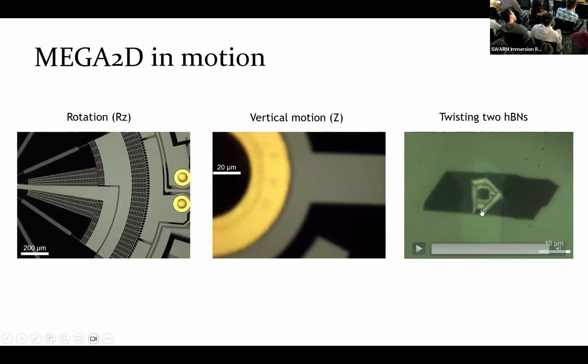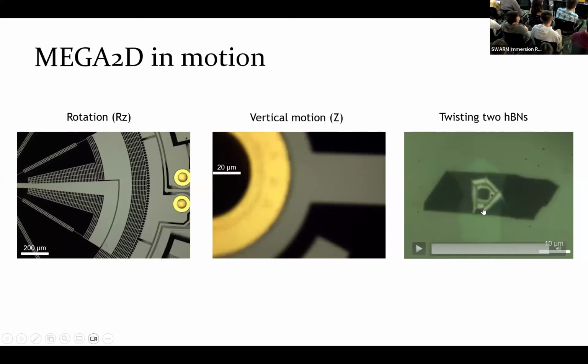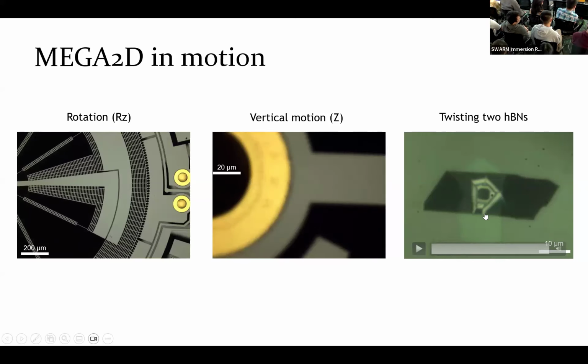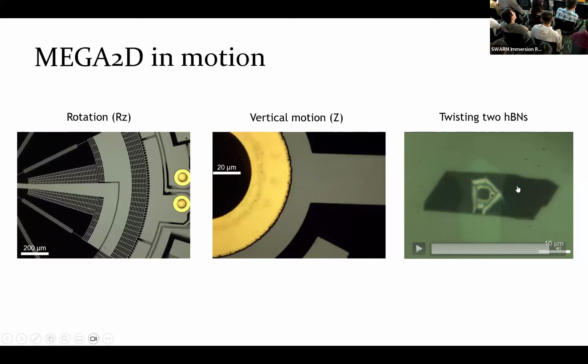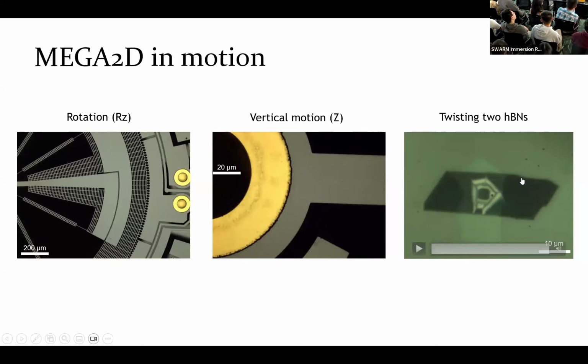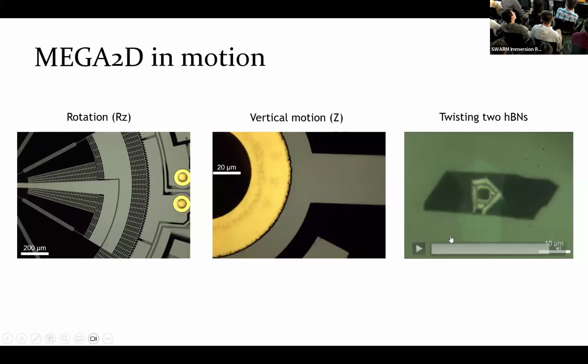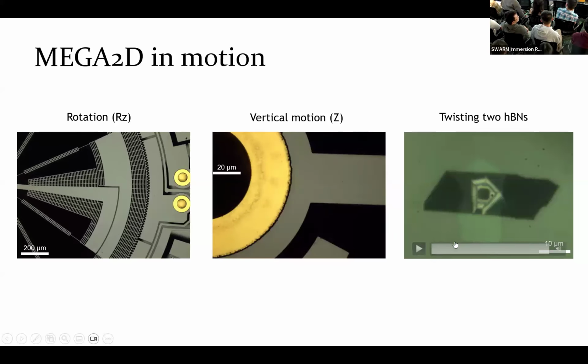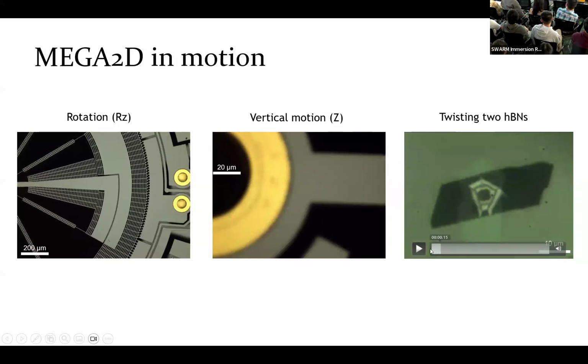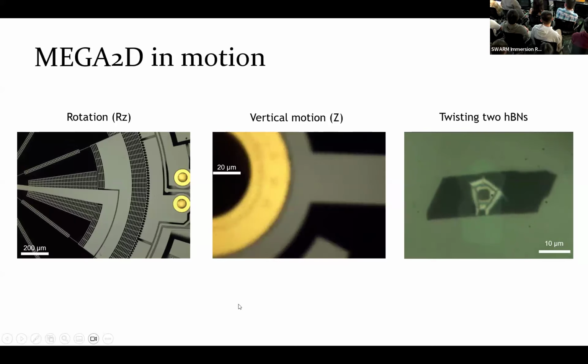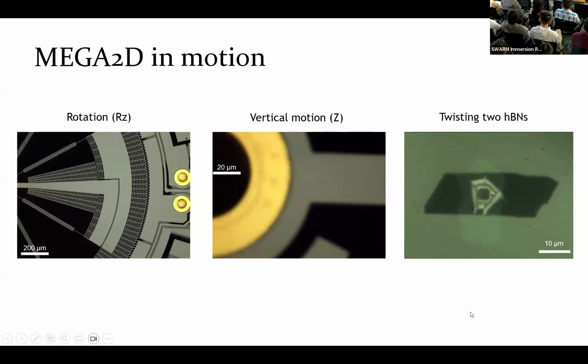And finally, this is a picture of an actual device where we have 2 layers of 2D materials. One is on the pyramid, that's the black one, and the other is this semi-transparent one, which is on the flat substrate. And we turn on the electrostatic motors, and you can see one layer rotate against the other.